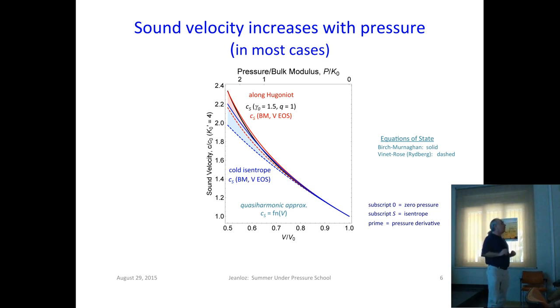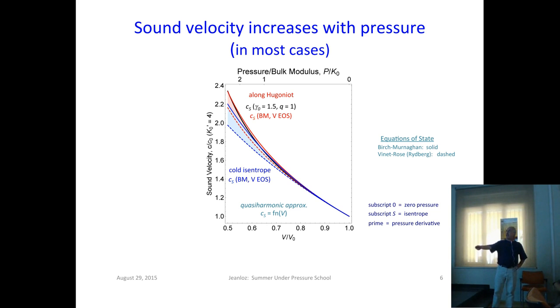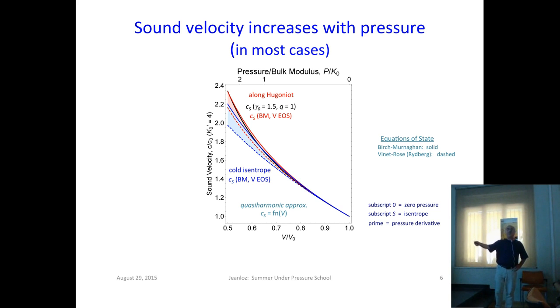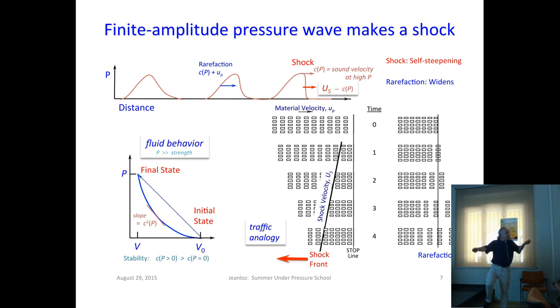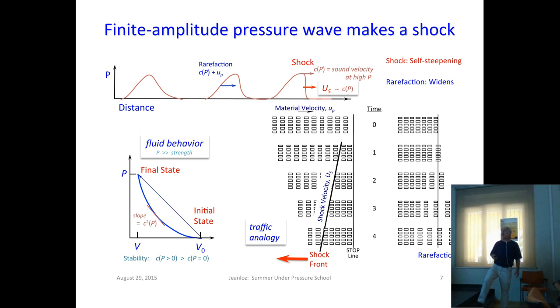The sound velocity of materials typically increases with pressure. I've calculated sound velocities along shock Hugoniots — shown by the black curve — and also using equations of state shown in blue. In general, sound velocities increase with pressure or with compression in most cases, and this is related to the stability of the material. If you have a fluid — ignoring strength effects — the pressure-volume curve for the equation of state is usually concave upwards, and the sound velocity squared gives us the slope. If the curve is concave down, that's an indication of some instability, typically a phase transformation.